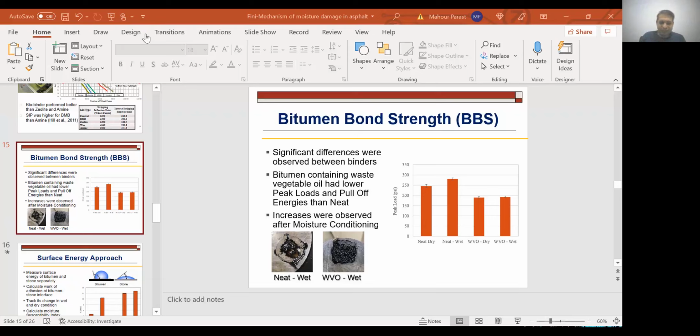Well, actually, when you think about mixture at different scales, when you go to a very, very small scale, you still have mineral fillers that are in contact with your bitumen. If we think about moisture wanting to break the weakest chain, the mineral filler interacting with bitumen is the first line of interaction. If that's not compatible, or the water can get into that interface, even if it's just a few microns in size, that's where the damage initiates.